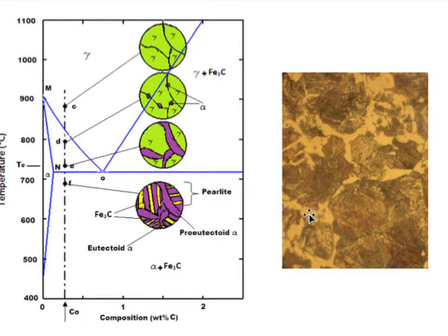We will look a little bit more now into the structure in a microscope. Here we see the microstructure as we saw it before, but now we're going to focus on the whole structure. The white phase is the ferrite, and the brown-grayish areas are the pearlite, as we learned before. Here we see a higher magnification, and now we're going to close up on one point that we recognized from before. We see first a pearlite area, original austenite grain, and here the white phases are the ferrite. We see how it has lined up in the original austenite grain boundaries.